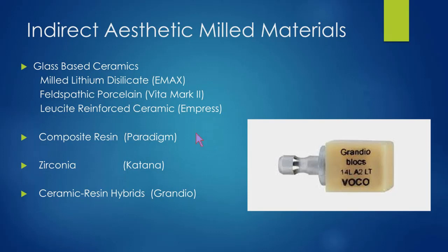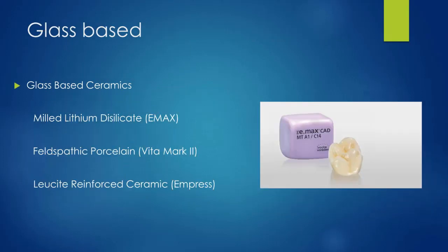We also had zirconia materials now available for milling. Very, very strong, obviously, sometimes too strong, sometimes can be abrasive. Have to spend a lot of time on polishing. That does require going into a sintering oven, so they can be very time consuming, and aesthetics can certainly be of concern. Going back to the composite resin, we don't get that luster that we would get when we were looking at some of the glass-based ceramics. And just as in composite resin, zirconia, even though there are some prettier materials like Katana, we still are not getting the kind of aesthetic results that we are with ceramics. And from this next category, called the ceramic resin hybrids, and namely we're going to be talking about Voco's Grandio block, and I'll talk to you about that category of materials here in just a second.